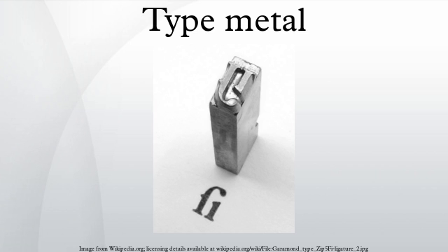Zinc. Brass spaces contain zinc, which is extremely counterproductive in type metal. Even a tiny amount, less than 1%, will form a dusty surface on the molten metal surface that is difficult to remove. Characters cast from contaminated type metals such as this are of inferior quality, the solution being to discard and replace with fresh alloy. Brass and zinc should therefore be removed before remelting.